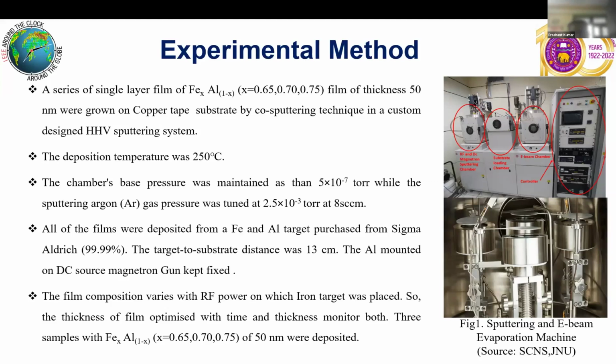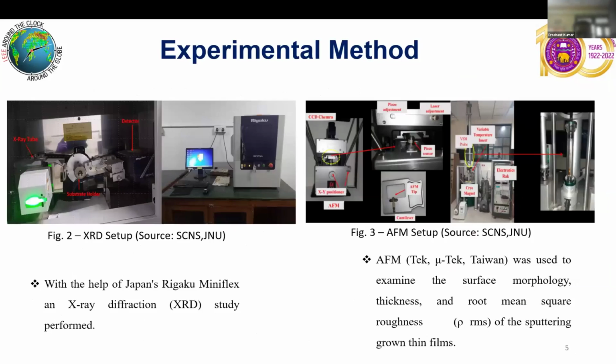The deposition temperature was 250 degrees Celsius, and the chamber pressure was 5 × 10⁻⁷ torr. Argon pressure was 2.5 millitorr. The targets used for this were from Sigma, and the thickness was maintained at 50 nanometer using the thickness monitor. This is the instruments which we have used for the characterization: the XRD from our center, and AFM for measuring the roughness of the film.